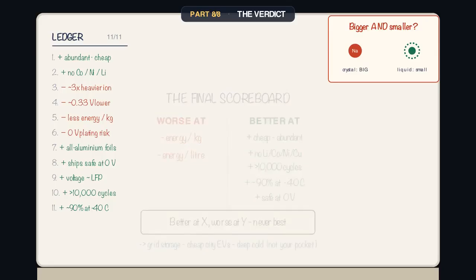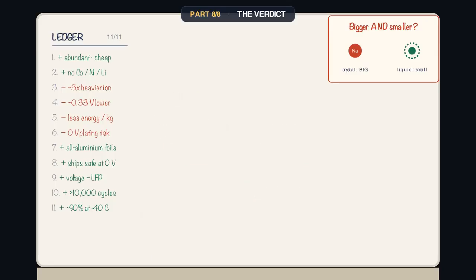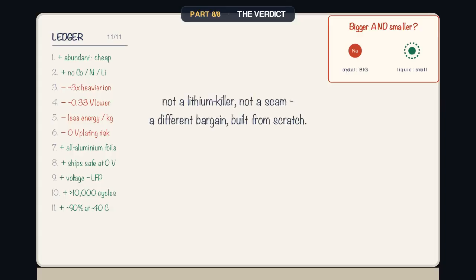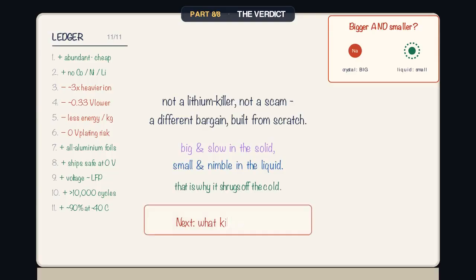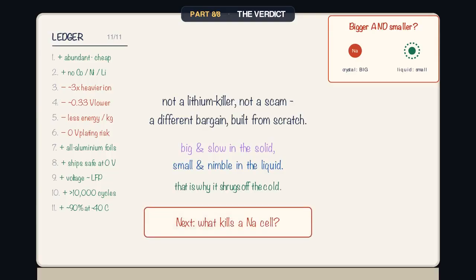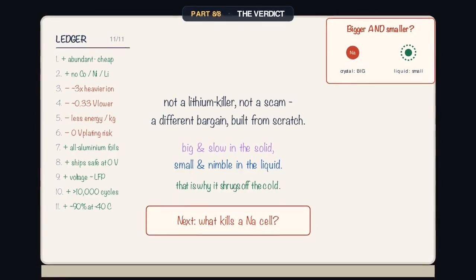Not your pocket. So the honest one-liner: sodium is not a lithium killer, and it's not a scam, it's a different bargain, discovered part by part on this board. And that opening paradox turned out to be the whole thesis. Big and slow in the solid, small and nimble in the liquid, which is exactly why it shrugs off the cold. We built the cell. Next time, we push it hard: fast charging, degradation, and what actually kills a sodium battery. Bring the ledger.